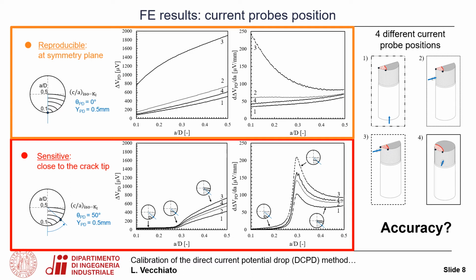To study the effect of the position of the current probes, the position of the potential drop probes was fixed. In particular, the first configuration chosen was the most reproducible one, so locating the potential drop probes on the crack symmetry plane. And the second one was the most sensitive one, so locating the potential drop probes as close as possible to the crack tip, whenever the crack has a normalized crack depth of 0.3.